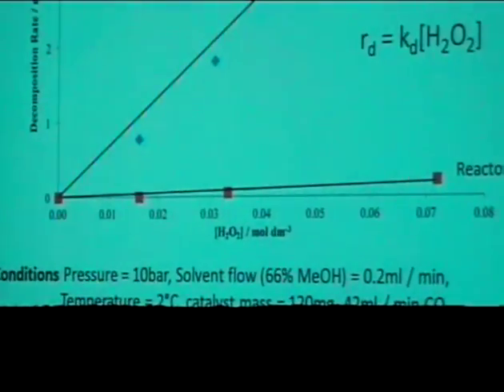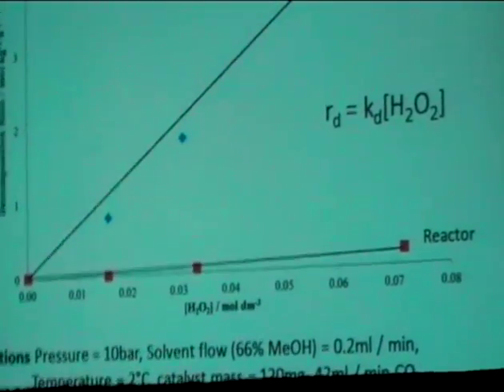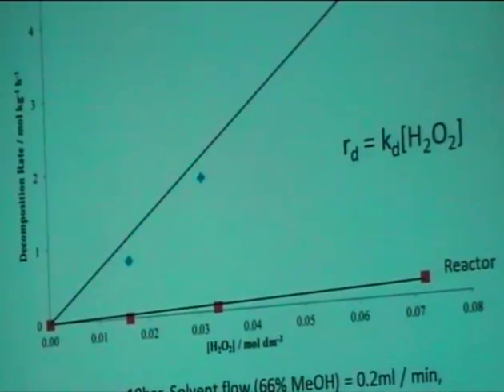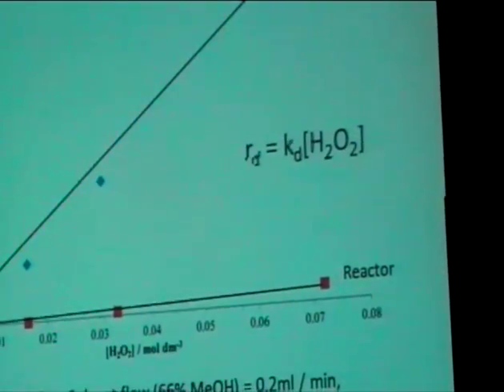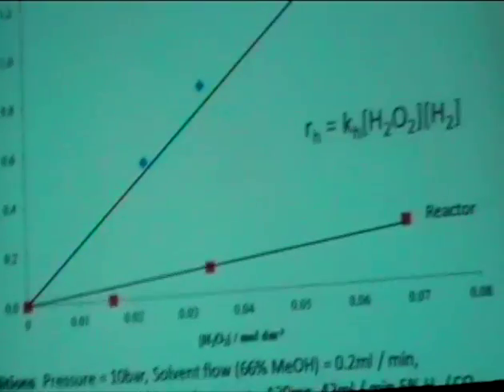We put a hydrogen peroxide feed in and we've measured the rate. As we can see, there's a linear trend, and we can approximate this to a physical contribution from the reactor. We can do the same, and we can see that this also is a first order trend. Very similar, we vary the hydrogen peroxide or the hydrogen.